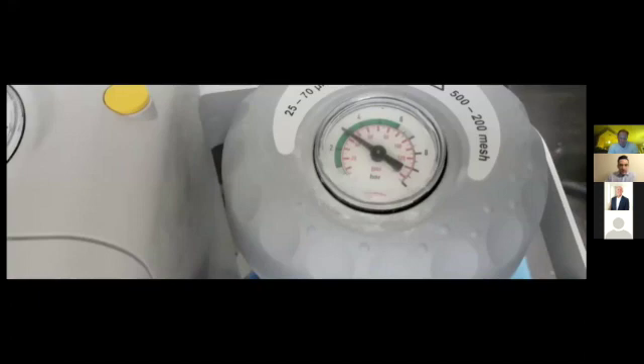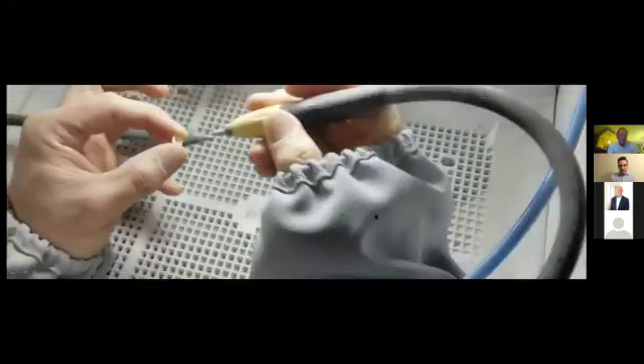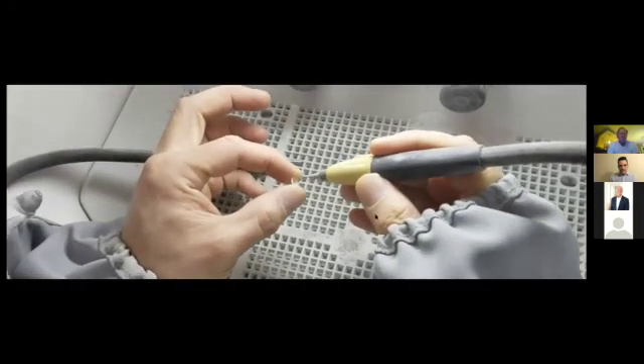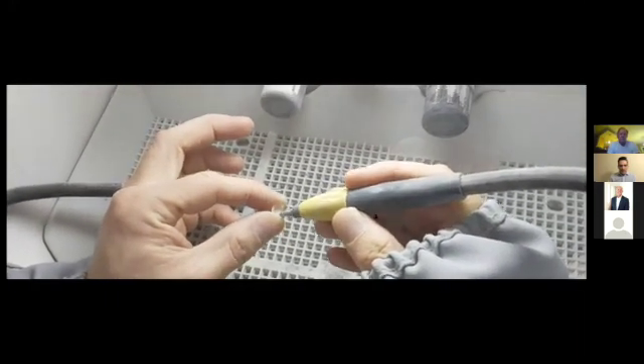With zirconia, you cannot etch it with hydrofluoric acid, so you have to sandblast it to bond to it. So one question will be, if you sandblast zirconia, does it actually do anything to the zirconia surface? Here we've taken some zirconia specimens and we're sandblasting them in our sandblaster. We use 50 micron alumina for 10 seconds at 2 bar pressure.